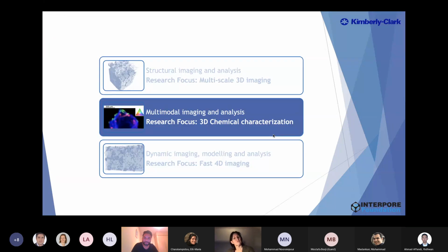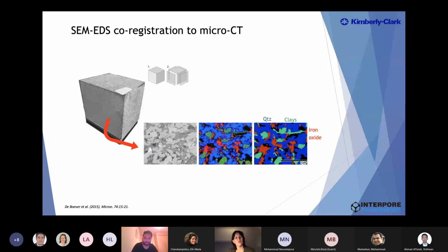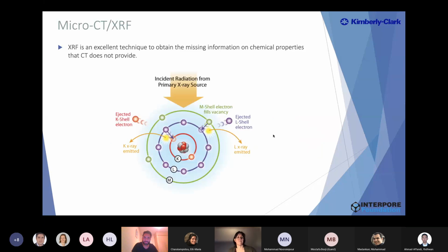Then the next thing is 3D chemical characterization, because besides structure, chemical characterization is also crucial when understanding rock behavior. As I mentioned before, you can combine, for instance, CT with SEM-EDS by co-registration and try to get an idea about the chemical composition. You can also combine micro-CT with X-ray fluorescence, because this is an excellent technique to give you information about chemical properties that cannot be detected with X-ray CT.